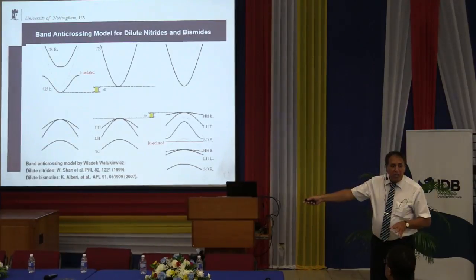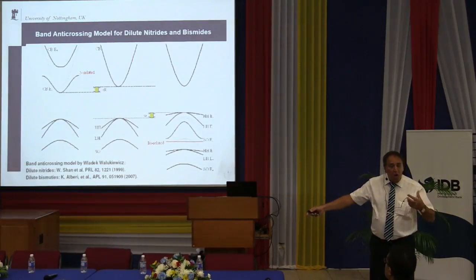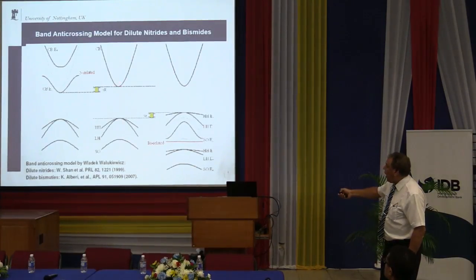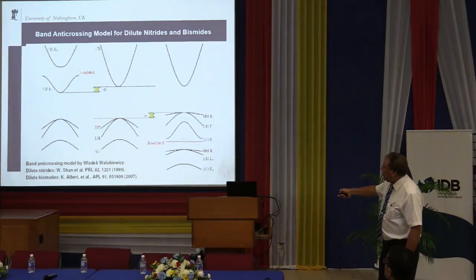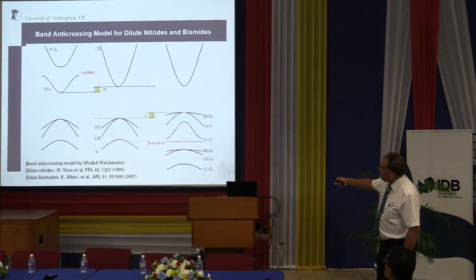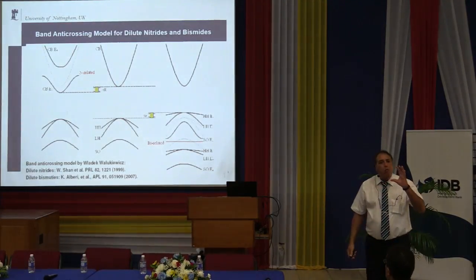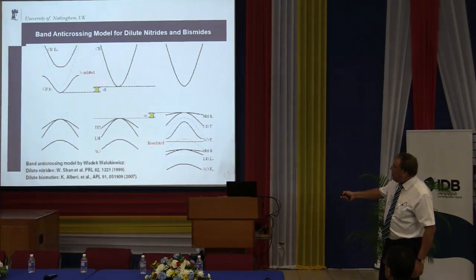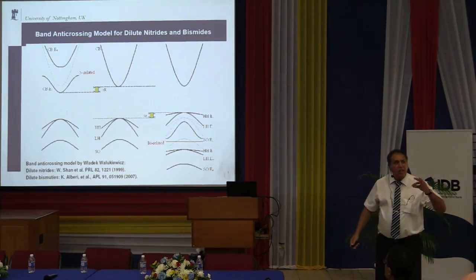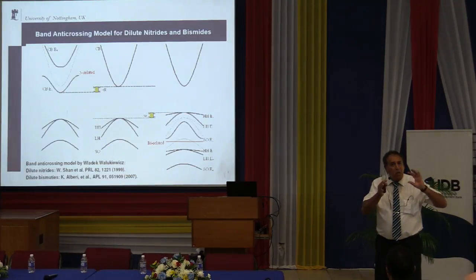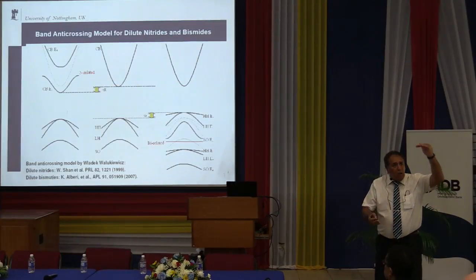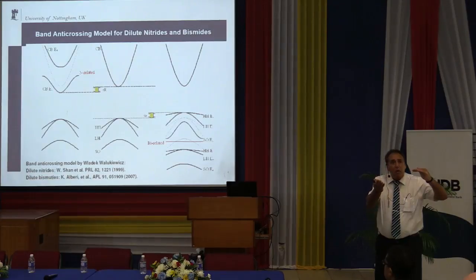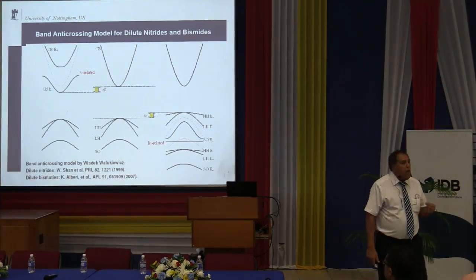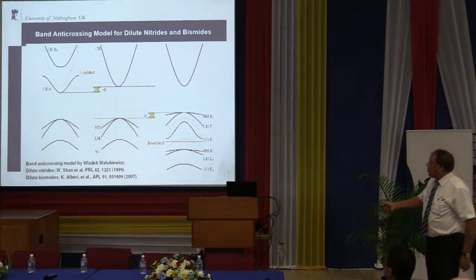I don't want to bore you with this because it's much more physics. You see, this is just the energy, because usually this energy I've been telling you to absorb is what you call a forbidden gap. These are the conduction band and the valence band, and usually when you shine light, you just use this forbidden gap, which is 1.4 electron volt. By adding nitrogen, this energy here drops to this point. If you add bismuth, this valence band goes up. So nitrogen and bismuth affect the electronic properties of gallium arsenide in different ways. One decreases the conduction band, one increases the valence band, and therefore you can tune this energy as you wish to reach this 1 electron volt energy system.